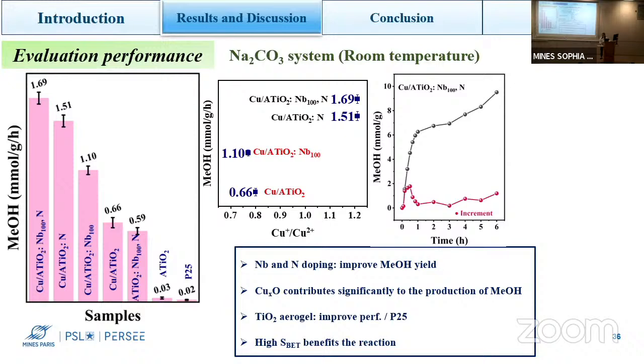Could this be due to alcohol? Because at the start you put some copper nitrate in alcohol medium. In some cases, for example for ruthenium, when we mix ruthenium 3+ or 4+, I don't remember exactly, in solutions, due to the large quantity of solvent and organic species, you see a reduction of the ruthenium.